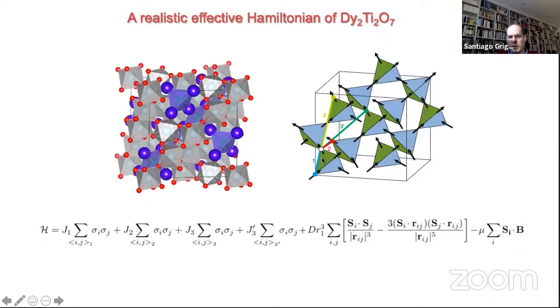And the simplest realistic Hamiltonian one can think of is one where you take into account nearest neighbors, next nearest neighbors, and third nearest neighbors. So you see that of the third type of nearest neighbors, you have two kinds. You have one kind which goes along this direction and the other kind that goes along that direction. Then the dipolar interactions and of course the interaction with the field. So the question was whether one could determine these from experiments.